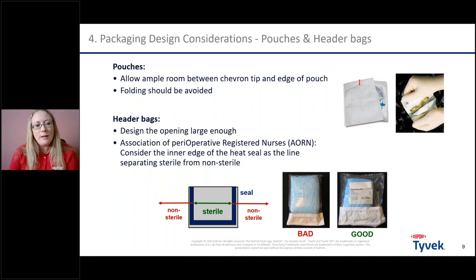Then in terms of header bags, you can see the pictures on the bottom. So one is very heavily filled and with a quite small window, and the other one is a little bit more of the space. So it should not be too heavily filled and too small window, because usually you will peel off the window and take the product out there. And also, real experiments have already shown with nurses, it is very difficult to aseptically present the content.